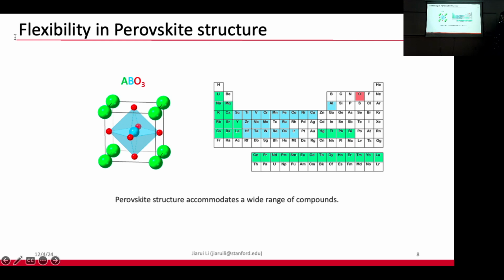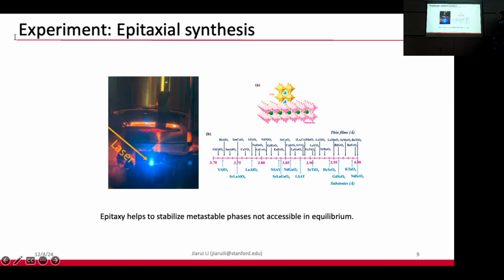And so there are a lot of combinations of elements that can be put into this structure, and therefore this compound can have a lot of choices. However, not every combination of the elements here is actually thermodynamically stable in the atmosphere, in the ambient condition. So in order to stabilize this metastable structure, we use an epitaxial synthesis technique to help stabilize these unstable new phases in the ambient condition.